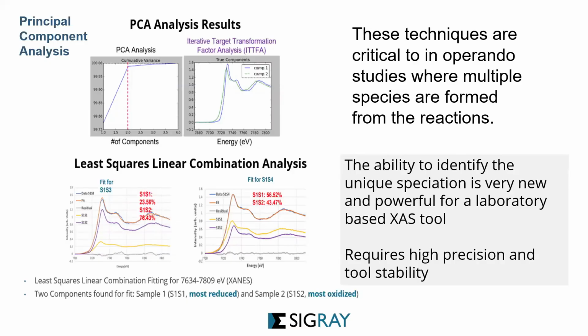To add to what SH is saying, another reason why this study was so interesting is that on a very modern NMC battery, the cobalt that we're measuring is far less than 2%. So it's an extremely challenging set of samples as well. Yeah, thank you, Sylvia. This ability to identify very dilute, very low concentration samples becomes very exciting and powerful. It made it possible that the laboratory system might be able to do many of the experiments that currently can only be done at the synchrotron. And by having very stable and reproducible results, now you can apply all these techniques that are only obtained at the synchrotron.